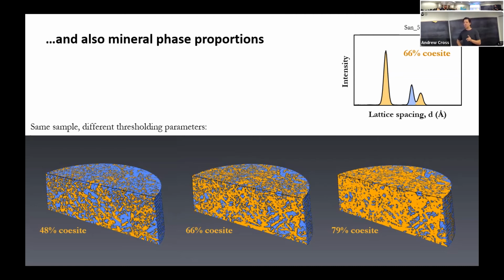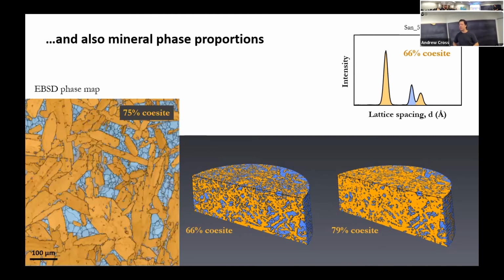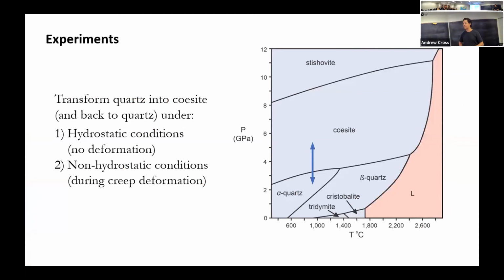We also do have other constraints from EBSD data. So this is where we've taken the sample, cut it in half, polished it down, and then looked at it in an electron microscope. And in this case, for a particular section through this sample, we've calculated about 75% Coesite. So we're able to predict with this method volume proportions within probably 10% or so, which is pretty good. It's good enough for what we need.